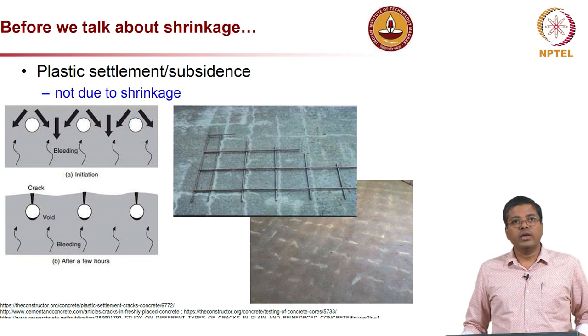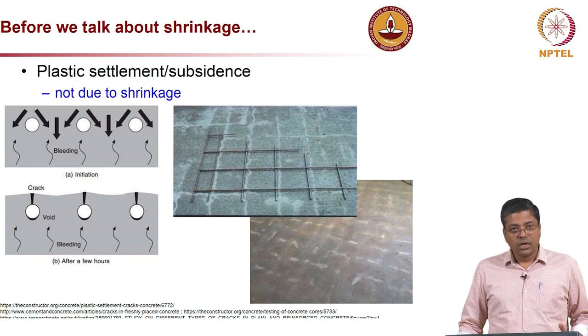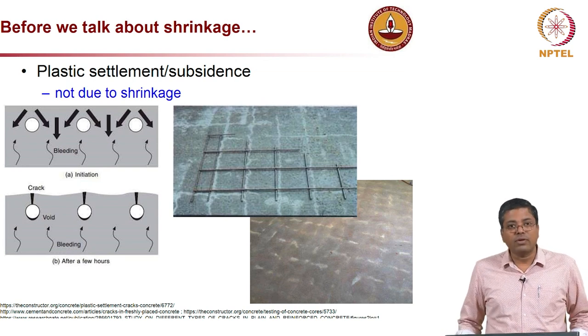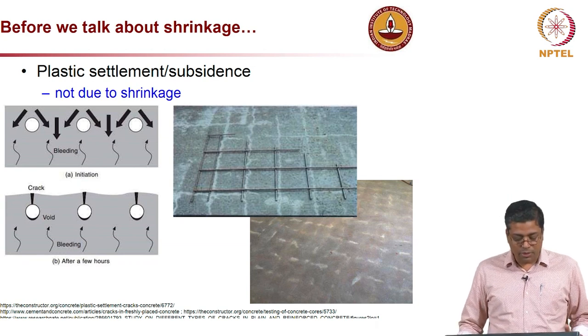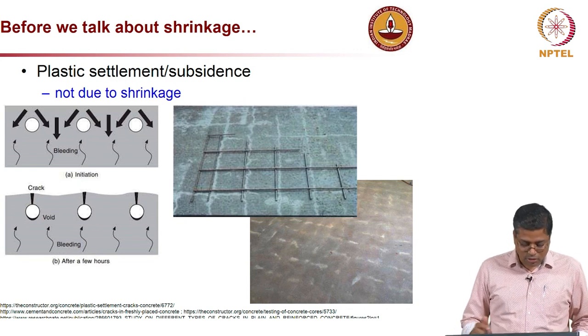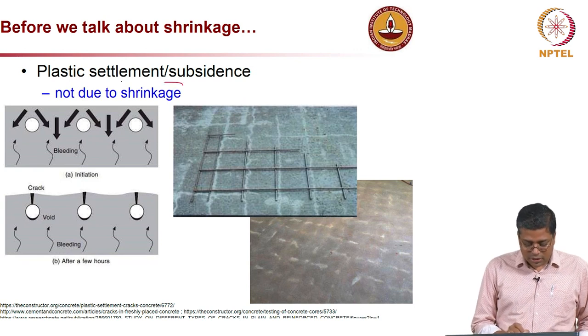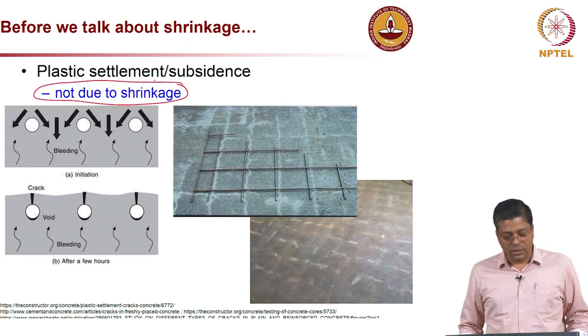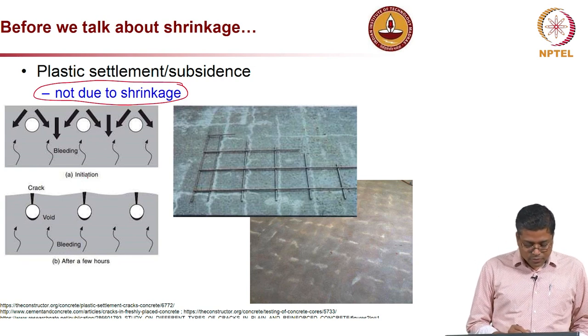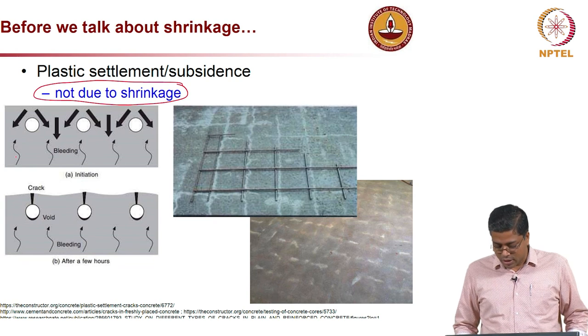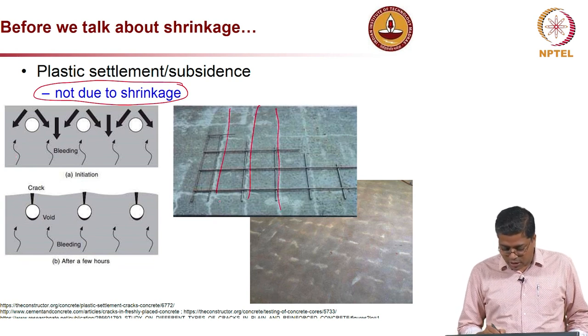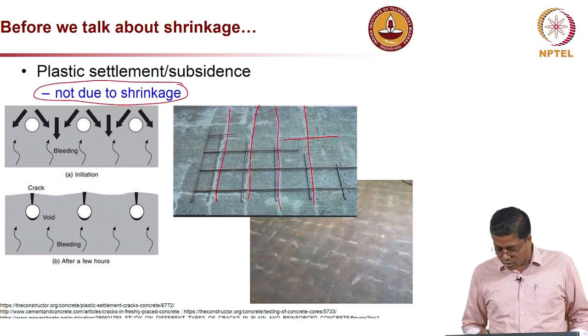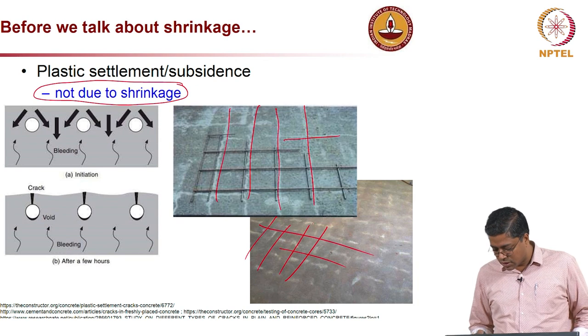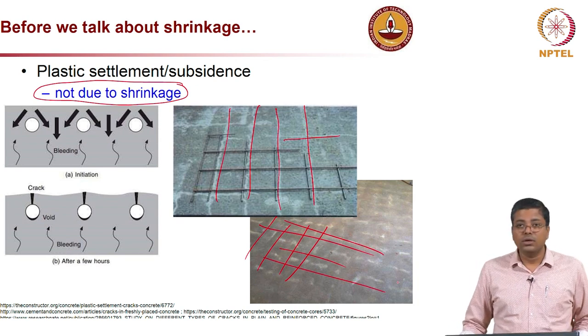Now, before we talk about shrinkage, there is one type of crack which is not because of the shrinkage, but because of the settlement of concrete during the fresh state, or in the plastic state. So it is not due to shrinkage, but I just wanted to cover this aspect also. As you can see on the two photographs at the top left, they show how it is manifested. They are actually forming right above the rebars. Here also you can see a pattern which is parallel to, or right above, the reinforcement.